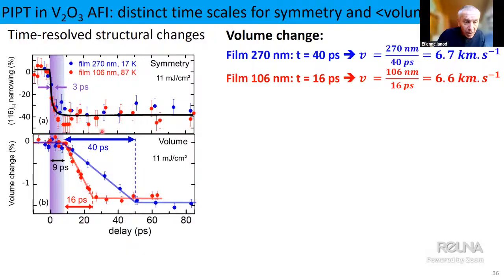Now consider the evolution of the volume. As you might have seen, we have worked on 2 films of different thickness, 270 and 106 nanometers. For symmetry change, thickness did not play a role, and it's expected if things occur at the level of individual grains. But the situation is very different for the volume change. You see now that the transition is faster for the thin film than for the thick one.